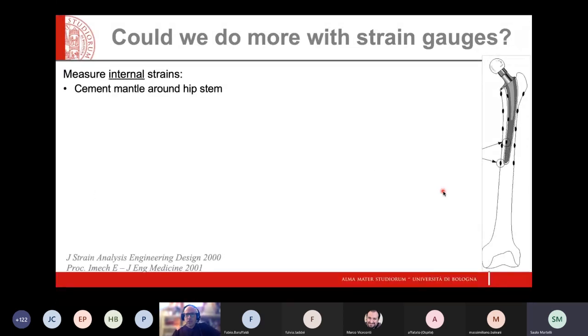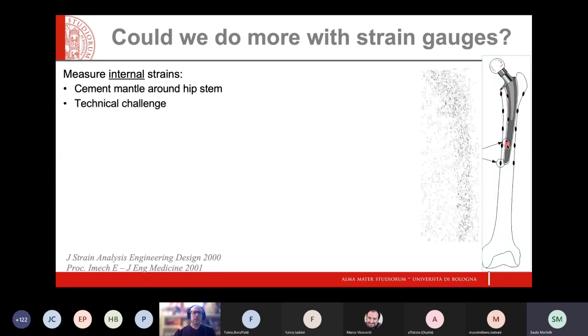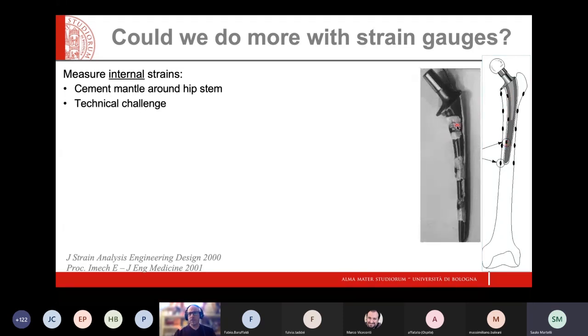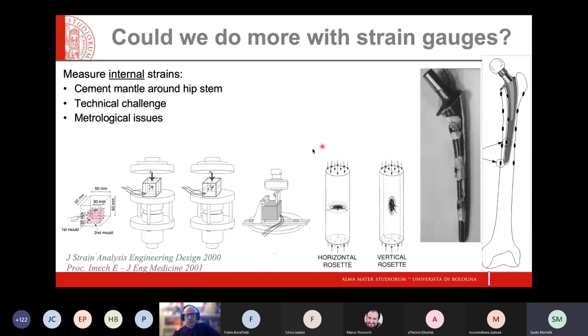We played with strain gauges also to measure something different. We tried to measure what happens inside. Strain gauges, as you probably know, are designed to measure surface strains, but we wanted to see what happens inside the cement mantle surrounding a hip stem. So we had to face the challenge of incorporating strain gauges in a known position and make them deform correctly together with the cement. And we also had to check that this would be reliable, so we designed a number of experiments to measure the errors or the artifacts induced by incorporating a strain gauge inside a material.